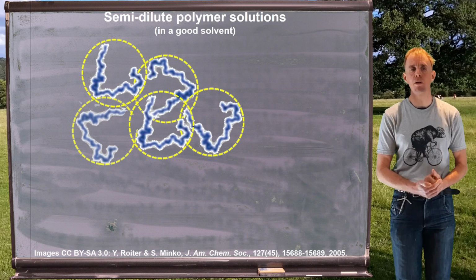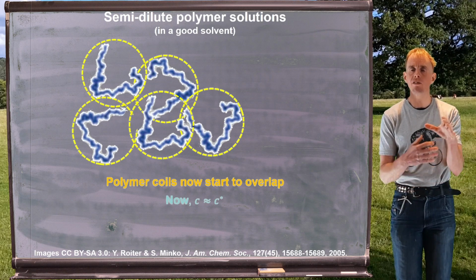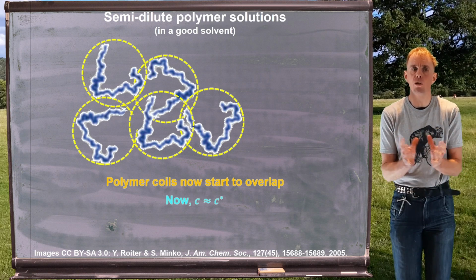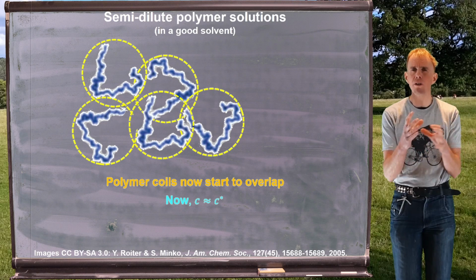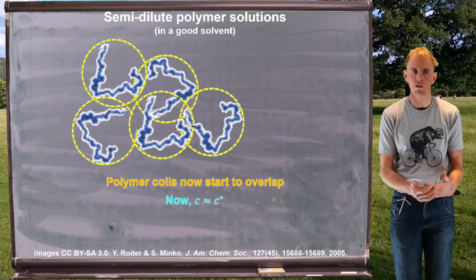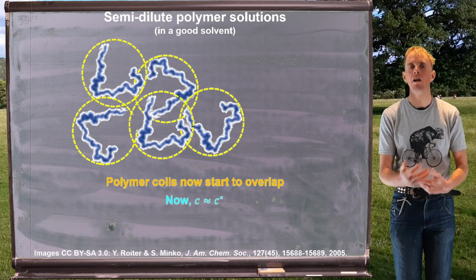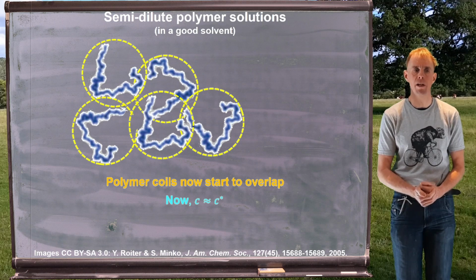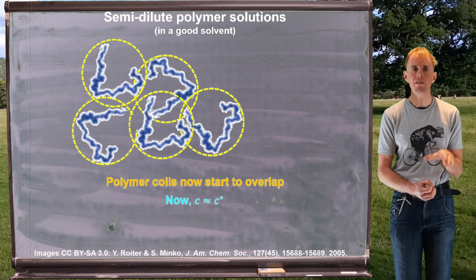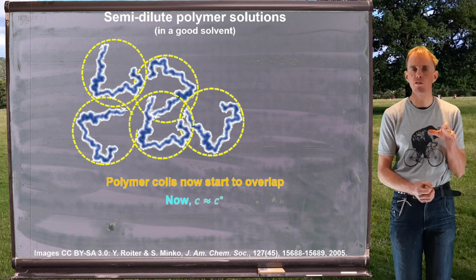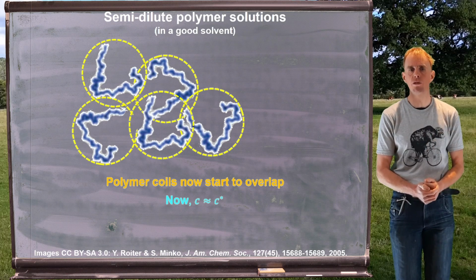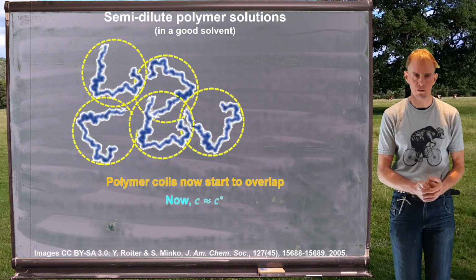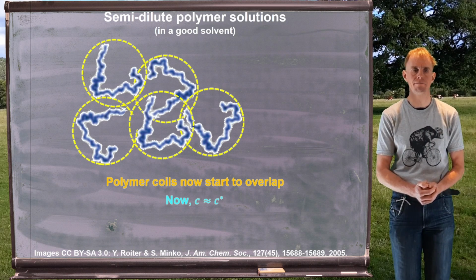And our semi-dilute polymer solution is where we get the space that a chain could occupy, those yellow dashed circles, overlapping with the spaces that other chains could occupy. And so in effect, we have polymer coils starting to overlap one another. This happens when the concentration of polymer is roughly equal to the critical concentration of polymer C star.